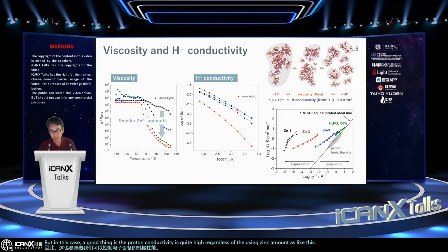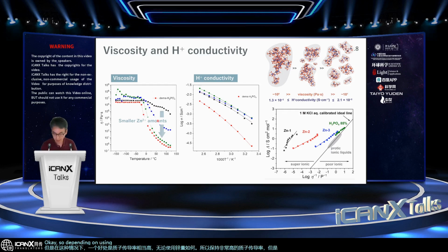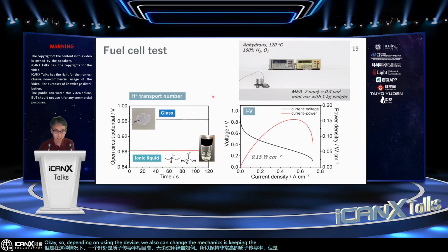So keeping the very high proton conductivity, but changing the mechanical properties. Depending on the device being used, we can also change the mechanics while keeping the very high proton conductivity. And as a result, by use of this kind of compound, we fabricated the very fundamental system of the fuel cell, as shown here.